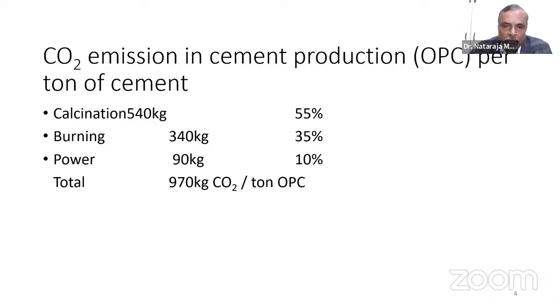Of course, we have different processes of manufacturing of cement, I'm sorry. So there is a calcination process which releases about 540 kg of carbon dioxide to the atmosphere, constituting about 55%. And of course, burning also produces carbon dioxide to the extent of about 35%, to be precise, around 340 kg. And we also need power, the energy part of the cement production, to the extent of about 10%, 90 kg, and all put together close to 970 kg, which can be rounded off to approximately 1000 kg.